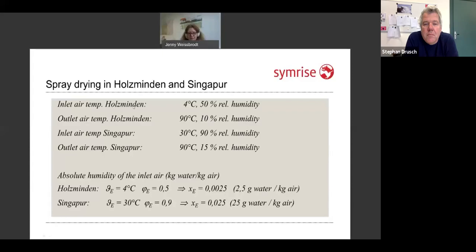This can be even the same question in summer or winter. If you take Holzminden for the typical winter condition and Singapore for the typical summer condition, you will see that you will have very different results just because of the weather. If we take these conditions of Holzminden and Singapore and look at the water in the air we use for drying, we can find out that our actual air in Holzminden will have around about 2.5 gram water per kilogram air. At the same time in Singapore, we'll have 25 gram water per kilogram air.